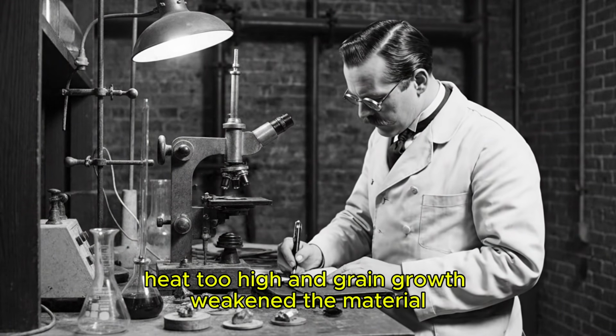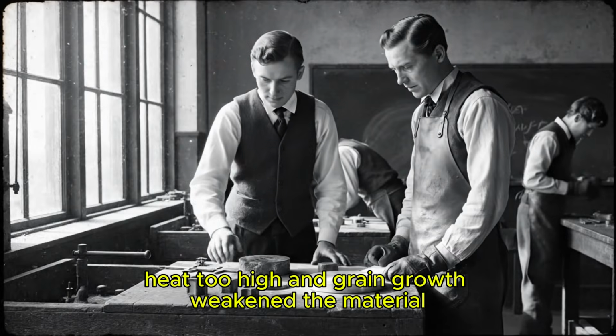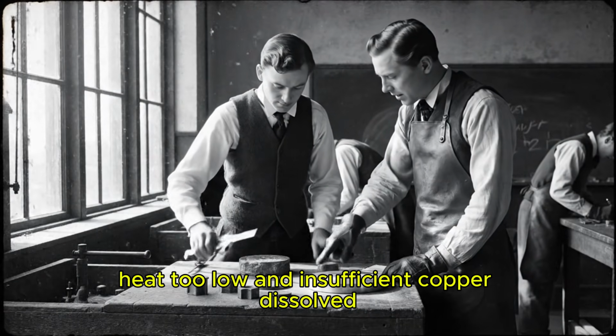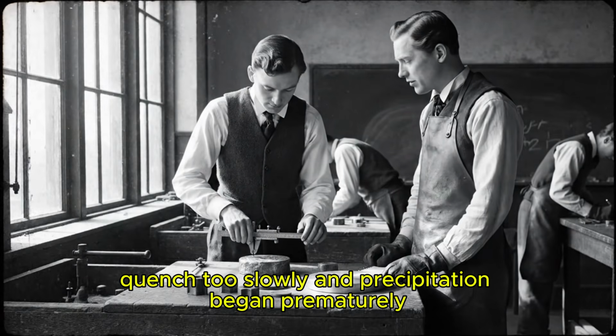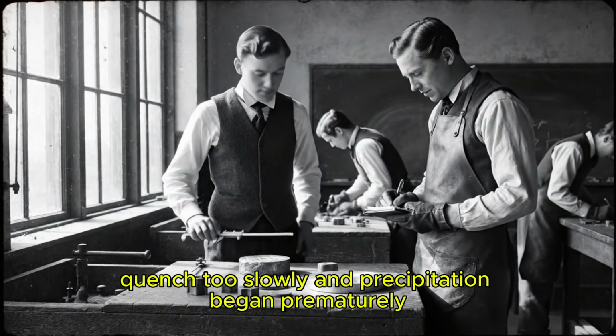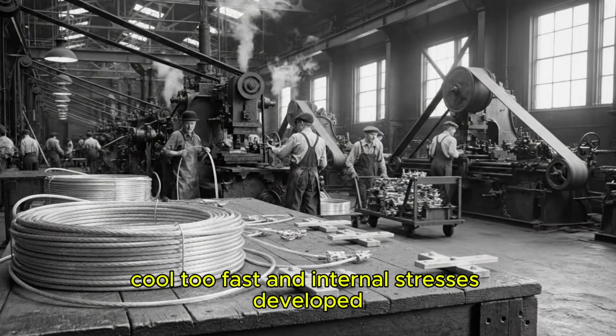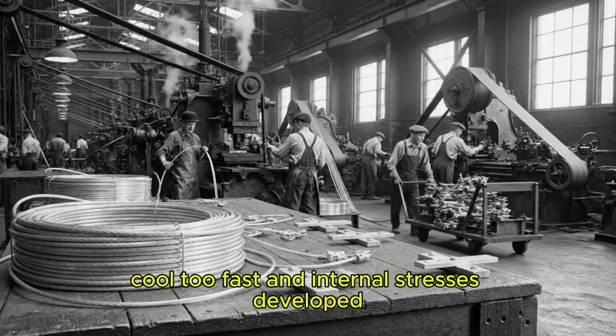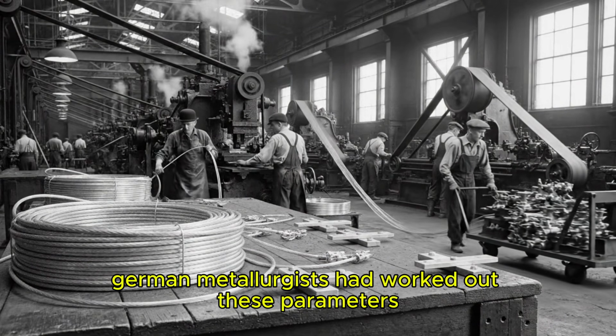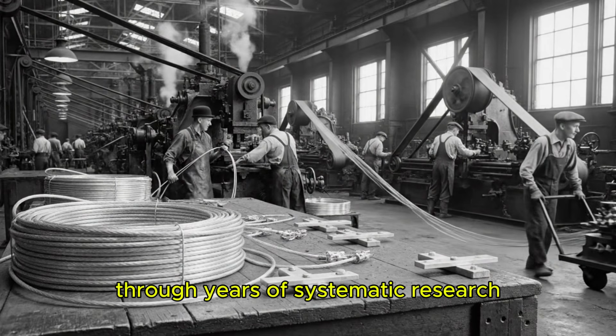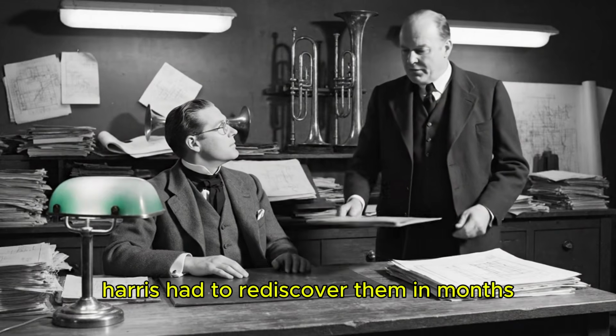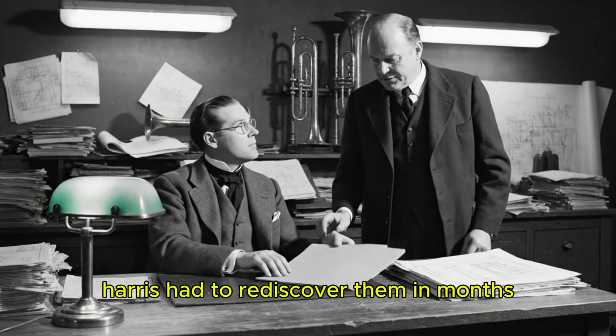Heat too high and grain growth weakened the material. Heat too low and insufficient copper dissolved. Quench too slowly and precipitation began prematurely. Cool too fast and internal stresses developed. German metallurgists had worked out these parameters through years of systematic research. Harris had to rediscover them in months.